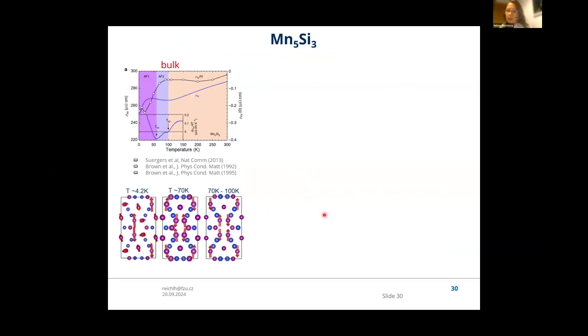So the last material which I want to mention is Mn5Si3. And this material is actually beautiful because it's just manganese and silicon, very simple elements, and they are grown on silicon in our case. Let me start by introducing that in the bulk, this material is known to have multiple magnetic phase transitions.